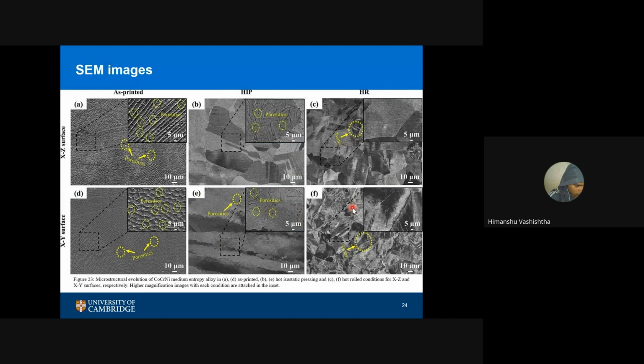So here is a good set of SEM images, for the XZ surface and the XY surface. In the inset, you can see the zoomed version of the places. For the as-printed specimen, you can see a lot of porosity, highlighted in yellow circles, a lot of porosity was there.